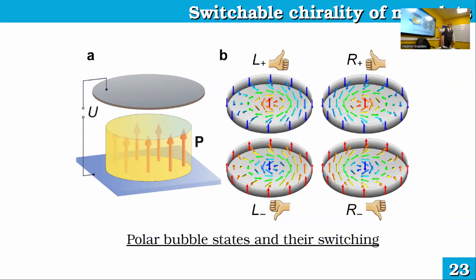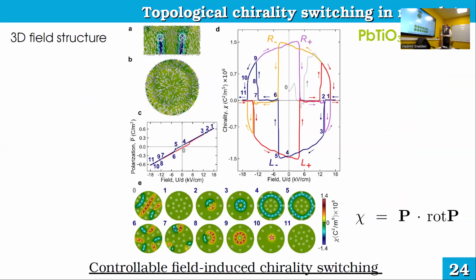So again, here's the experimental setup. The ferroelectric nanodot is confined between two electrodes. There is some space. It may be vacuum or some dielectric. And here we see the chirality switching protocol for such a nanodot. First of all, what is interesting, if you look at the hysteresis loop, it looks absolutely trivial. Nothing special about this behavior. It's like a normal hysteresis loop. Maybe it's a little bit narrow, but it doesn't matter. While chirality possesses very interesting and complex behavior.